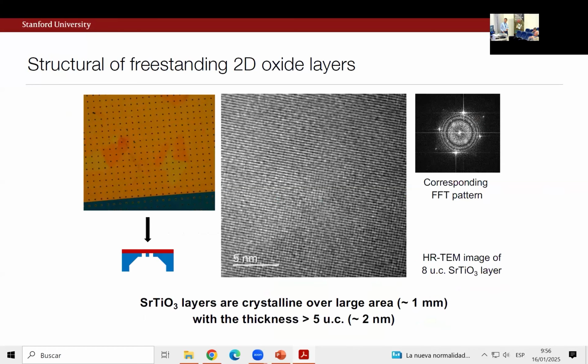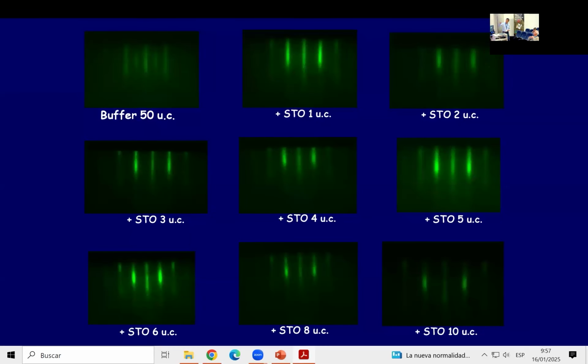I think that's a very good point, especially in thinking about the dynamics of the release. But I would say that the plan view TEM that I showed you, I think I showed you just down to 2 unit cells, but basically that picture wouldn't be able to generate this pattern, right? So I agree with you that this might be relevant for the dynamics and, let's say, the damage or fluctuations induced by this. Actually, it's also a good point that presumably as you vary that soluble buffer layer thickness, the occurrence of these things would change. Yeah, so that could be.